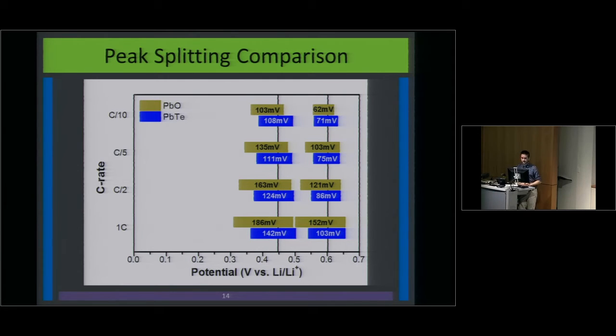And here, bigger is not better. The lead telluride only increases a little bit as you increase in C rate. So what this is saying is that the reactions are much easier to perform with the lead telluride.